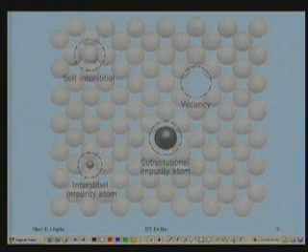Thereby they are compressing all the neighbors here, the electron clouds. And in this volume which I have shown here, the energy of the material has gone up because the electron clouds are compressed. So the enthalpy has gone up. This is called an interstitial defect or interstitial impurity atom. This is a crystal imperfection. Here you see the crystal is perfect, but not right here.